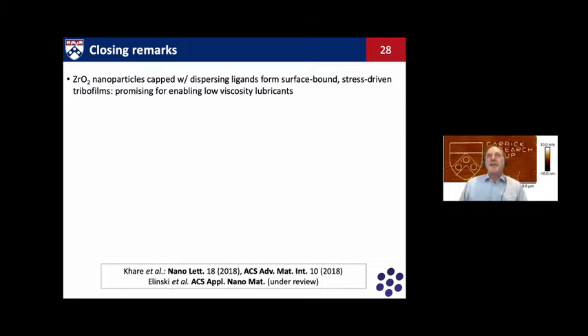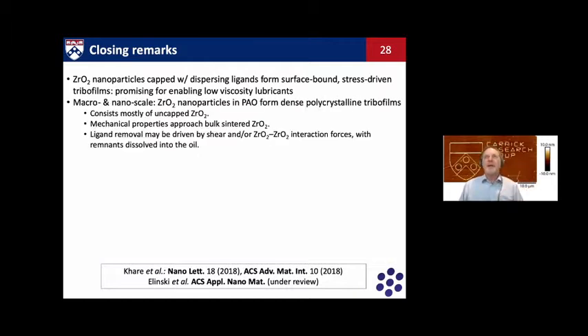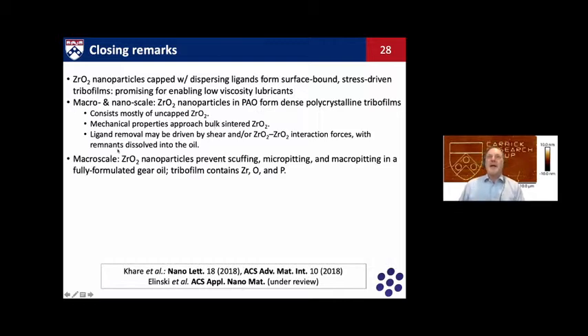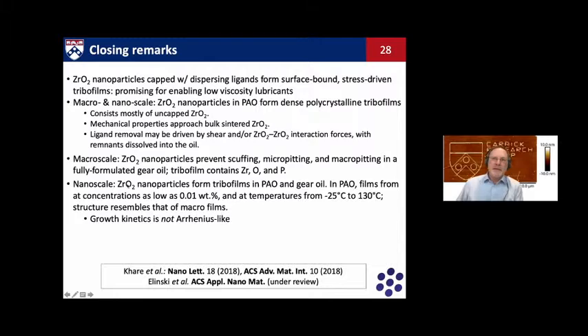So to close, what we see is that, like ZDDP, we can get tribofilms with solid nanoparticles. They are dispersed with ligands into the oil, but the ligands are stripped off and can form surface-bound tribofilms driven by the tribological stresses. We see that the films have properties approaching that of bulk sintered zirconia. We see benefits in terms of scuffing and pitting, macro pitting, even in a fully formulated gear oil. And that gives us some excitement about using this in applications.